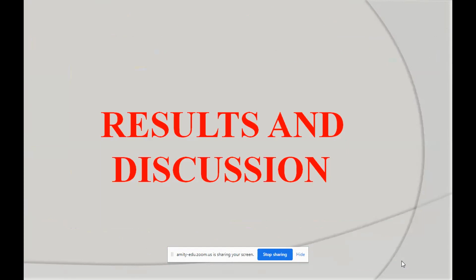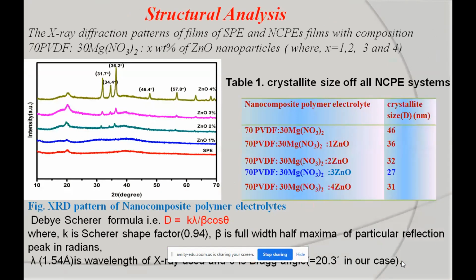Results and discussions. Firstly, structural analysis of this film confirms that the electrolyte prepared was formed. This is the XRD pattern of our nanocomposite polymer electrolyte. From this figure, we observe that peaks of the dispersed nanoparticles are observed. This confirms complexation of the electrolyte.